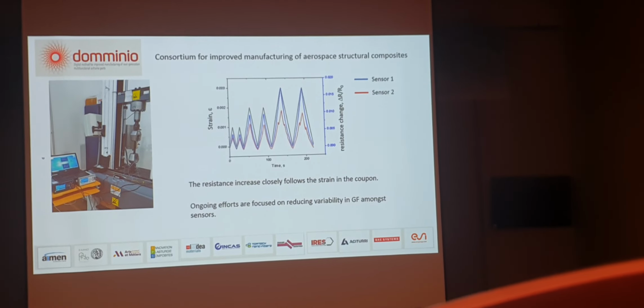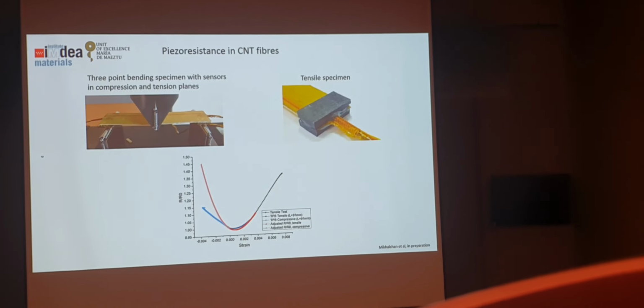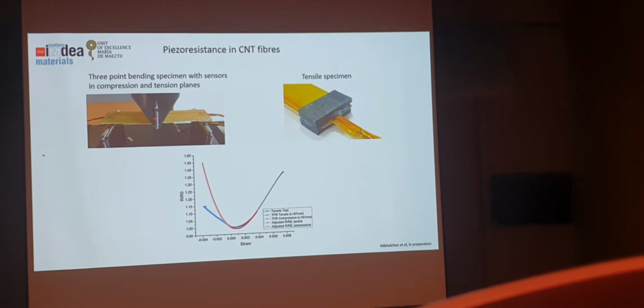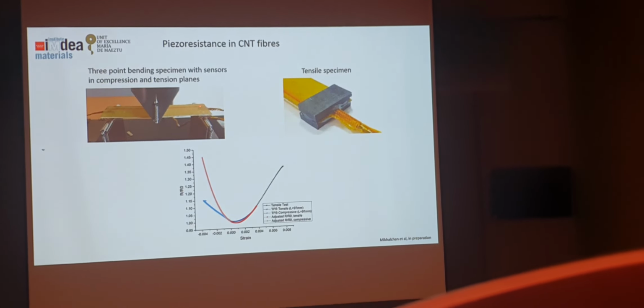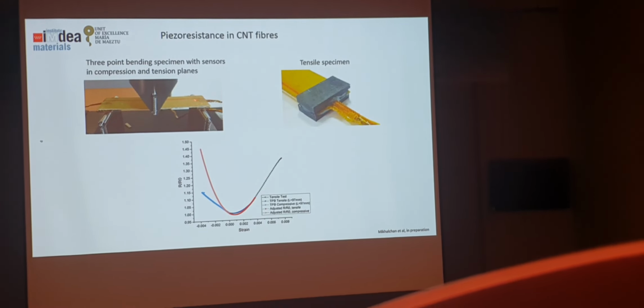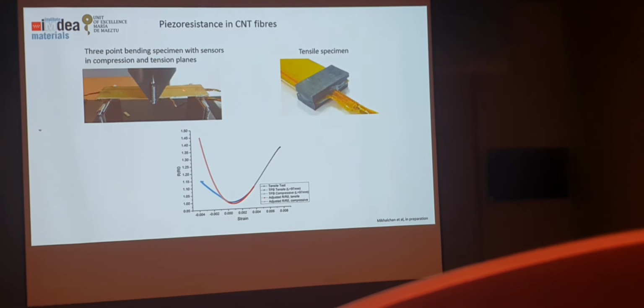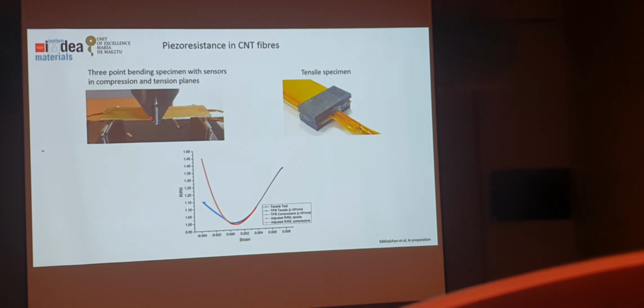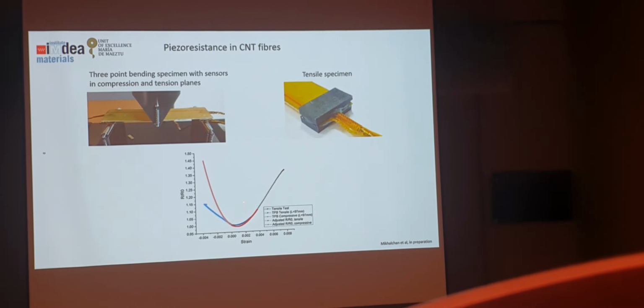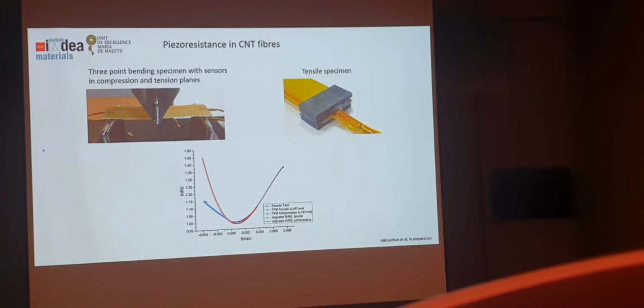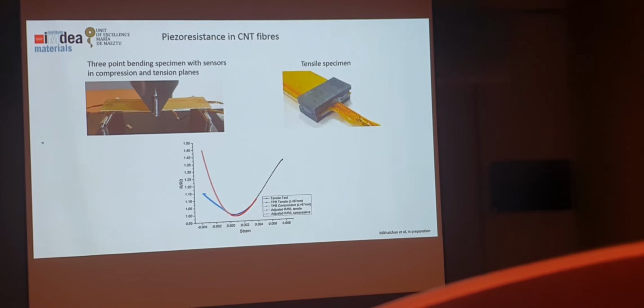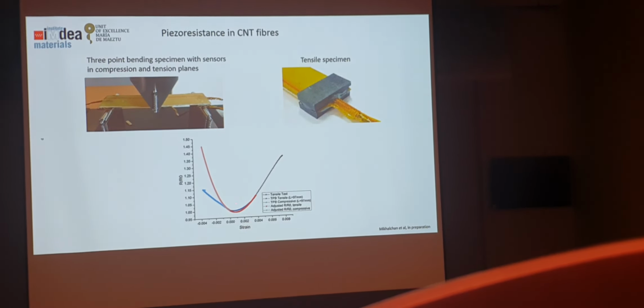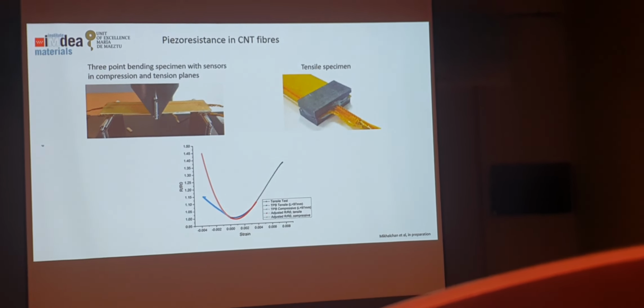But anyway, the problem that has been bothering me is, where does this piezo-resistance come from? A while ago we made some samples where we put filaments in. We knew that the piezo-resistive coefficient was positive in tension, so we thought, well, what about compression? So we made specimens for 3-point bending, one in tension, one in compression. What you find is that actually all of it falls on a master curve. This is just a normal tensile test, then this is the specimen in tension in the 3-point bending experiment, and this is in the 3-point bending compression.